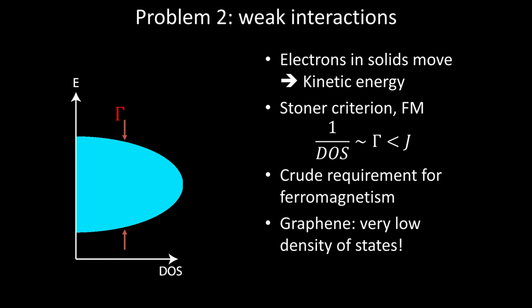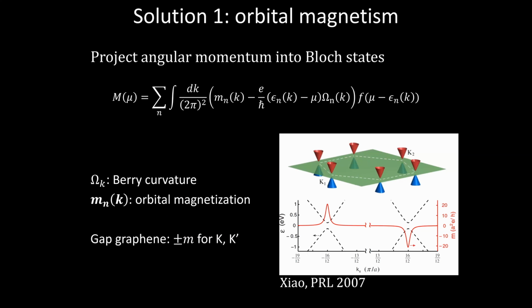The other problem is that when we think heuristically about what makes a ferromagnet, you have some interplay, let's say in a Stoner picture, between the fact that electrons have a finite bandwidth, and it costs kinetic energy to have them occupy the same spin. So you need interactions to be strong compared to kinetic energy, right? And in graphene, you have a very large bandwidth. You have an 8 electron volt bandwidth and essentially very low density of states. In fact, it's vanishing when you're near charge neutrality, in this massless Dirac dispersion regime, which is where we do all of our experiments. Okay, so low density of states, no spin-orbit coupling. What are you going to do about it? Okay, so the answer to the question of spin-orbit coupling turns out to be sort of simple, which is don't use the spins at all. Right?